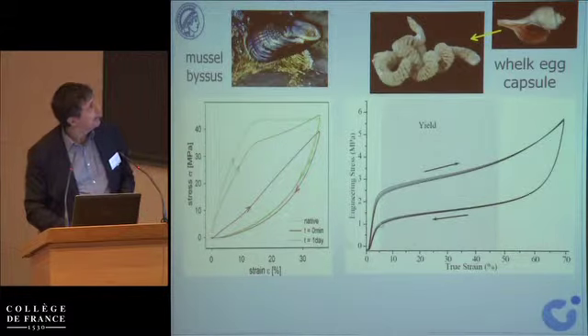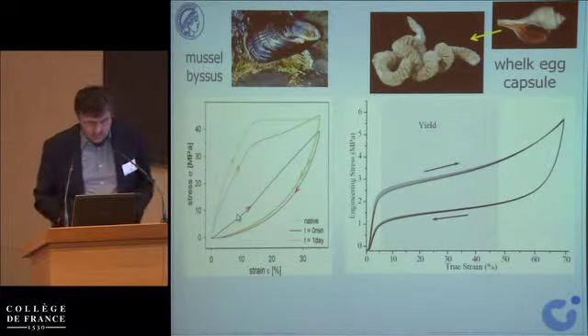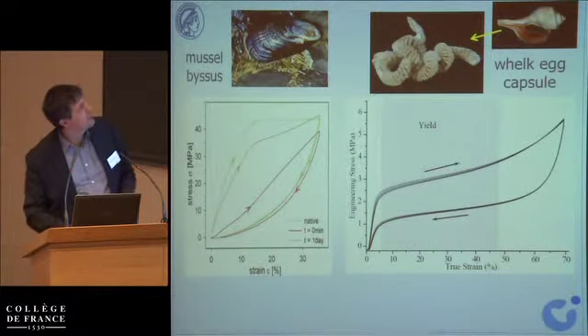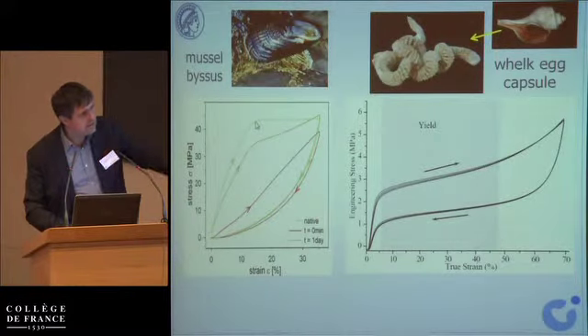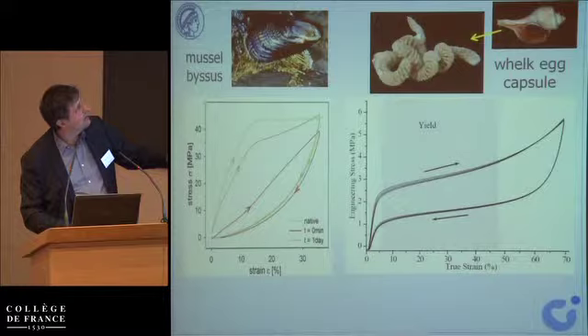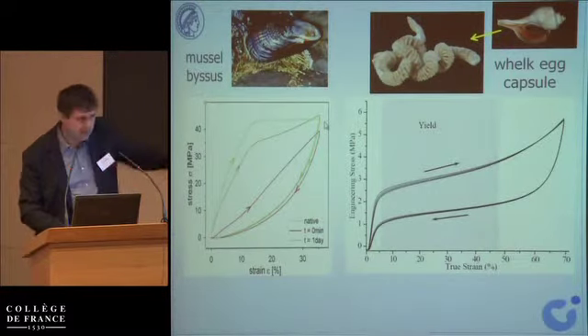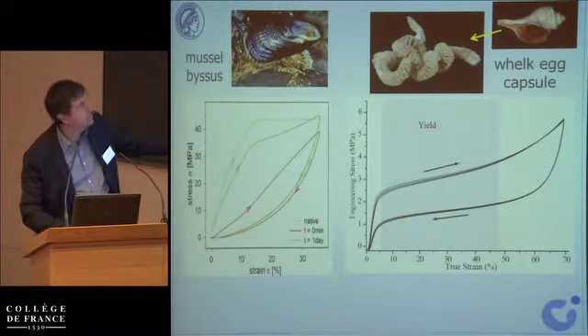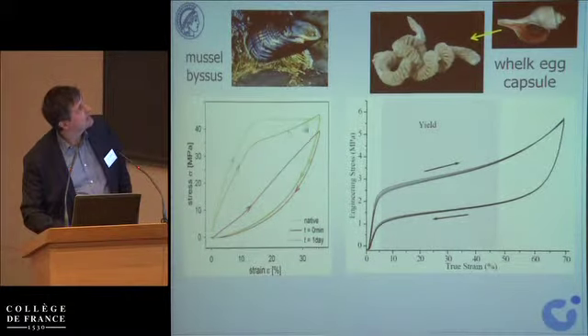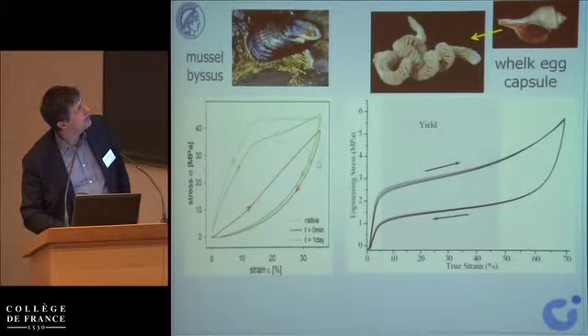This one has a slightly different behavior. This is now that fiber that is being stretched. Again, it's very stiff in the beginning, so the mussel holds to the rock until a certain point where the mussel really is torn away from the rock. And again, you have a very large deformation, which means that a lot of energy can be released, the mussel can move away. But interestingly, again, the fiber is not broken. And when it comes back, you see now it has changed properties.